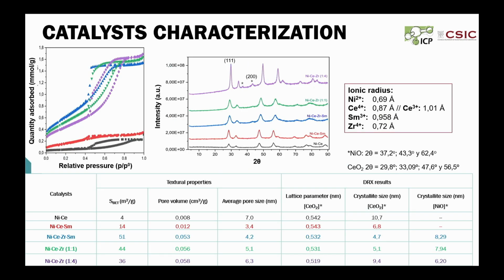So we characterized the catalysts. We found that all catalysts had nitrogen adsorption-desorption isotherms of type IV, characteristic of mesoporous solids, as we can observe in the table, and H2 hysteresis, characteristic of bottleneck pores, which can also be attributed to a non-defined distribution of pore size. The surface area of nickel ceria increased with the incorporation of samarium and zirconium in the structure.